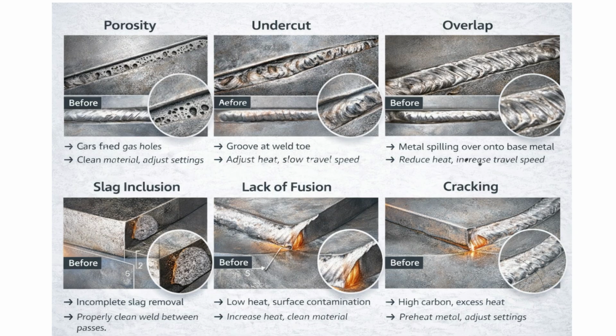Even experienced welders encounter problems. Let's identify common defects and how to fix them. Porosity appears as small holes or cavities in the weld metal, caused by gas trapped during solidification. Causes include contaminated base metal, moisture in the electrode coating, too long an arc length, or inadequate shielding. Solutions: clean the base metal thoroughly, use dry electrodes, maintain proper arc length, and check for drafts disrupting the gas shield.